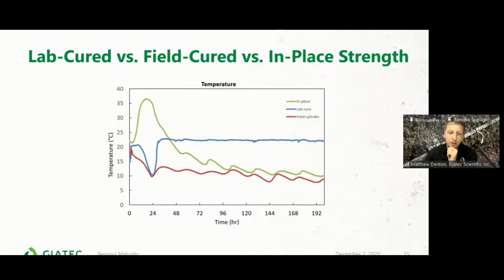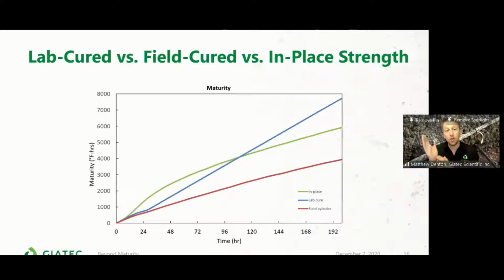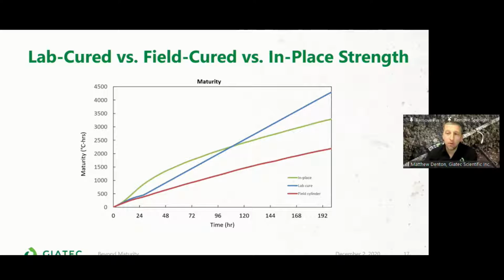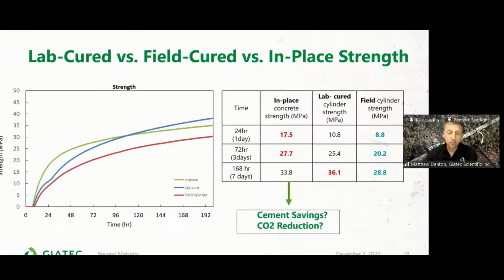So again, if we do a quick comparison here, we look at this scenario where we have this spike in the early temperature gain on the in-place concrete in our green line. Our blue and our red lines are samples that are taken. The red line is the sample of the cubes kept on site. So we can see quite a difference in the maturity line. And I think one graph that we're all familiar with, if we look at the strength graph, you can see that the early age strength is a much quicker gain, and then it plateaus out, whereas we're actually getting a very different strength curve from the sample that's taken on site versus the sample that's in the field. So just to quickly show here, if we have a look at this graph, we see there's the in-place concrete, we see lab cured, and we see field cured.